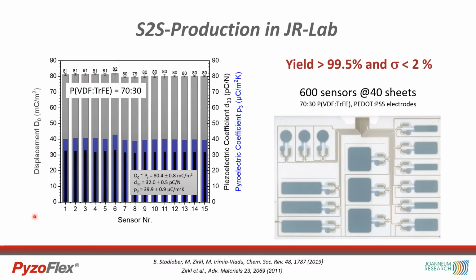Now I'd like to show some statistics for sheet-to-sheet sensor printing. For well-controlled printing conditions, the functional yield is beyond 99%, as demonstrated here, because all of the 600 sensors printed on 40 sheets were functional, and they had less than 2% standard deviation from the average remanent polarization of 80 millicoulomb per square meter. And this is a very high value for a copolymer composition of 70 to 30. We also see less than 2% standard deviation in the measured pyro- and piezoelectric coefficients, which is also quite nice.